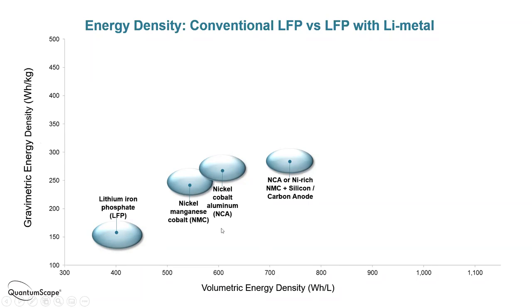So I mentioned NCA, that's nickel, cobalt, aluminum oxide. That's most common in Teslas with among the longest range of vehicles on the market. NMC is a very similar material, a little bit more stable, made of nickel, manganese, cobalt, and it's just a little bit worse in terms of energy density. The next generation, what we're going to see over the next few years, are based on very similar cathodes with a little bit of silicon added to the anode, and that gives you another bump in energy density up to the, say, 700 watt hour per liter range.